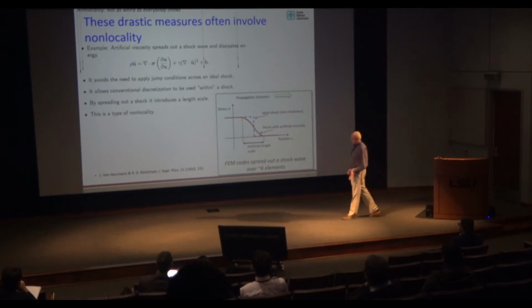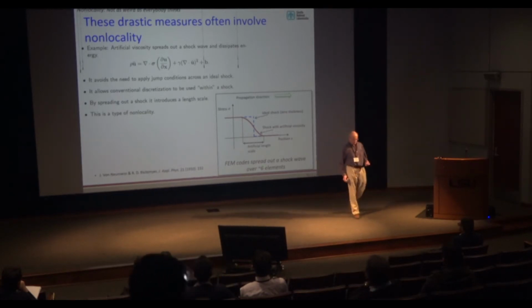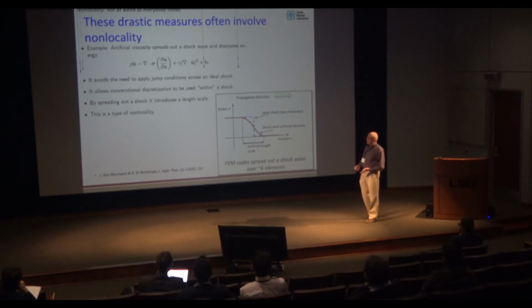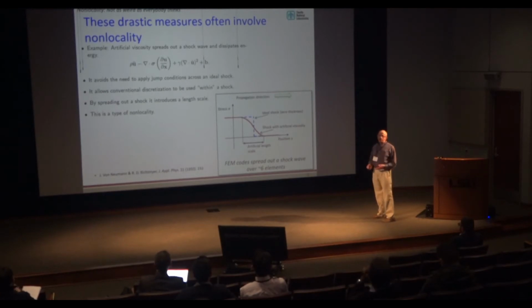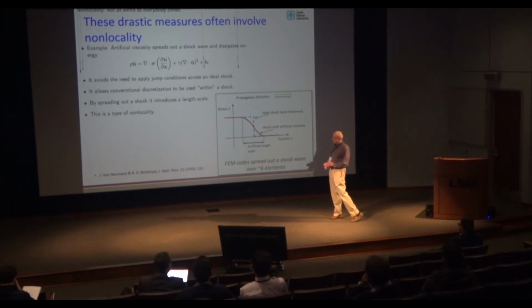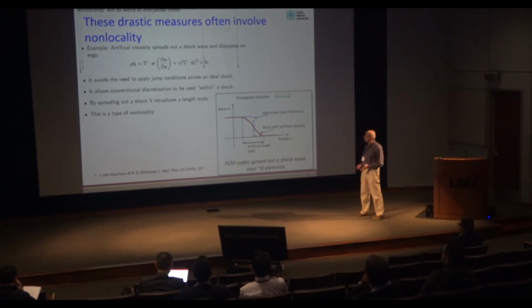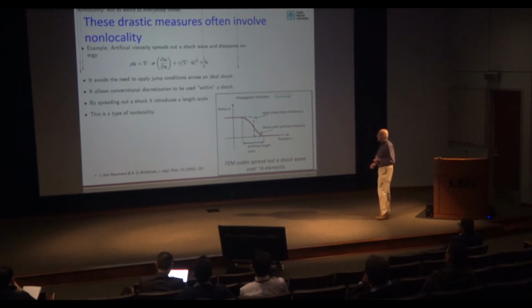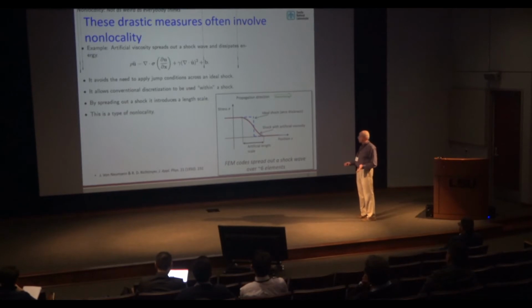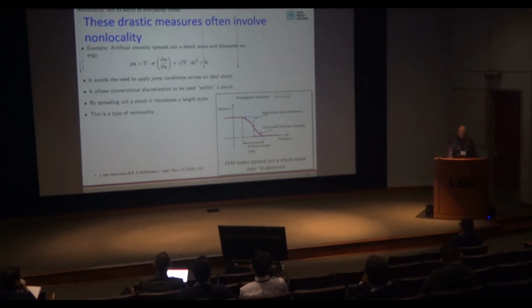You can apply the difference formulas or finite element formulas without worrying about this non-physical noise that would otherwise occur. It also happens to dissipate exactly the right amount of energy to be thermodynamically consistent with the actual thermodynamic path in a shock wave. But my point here is that artificial viscosity, which everybody uses, is a non-local term. It introduces a length scale, which is artificially chosen to be about 5 or 6 element widths. Therefore, what you end up with is a non-local approach to solving a mathematical system that was nominally local to start with.